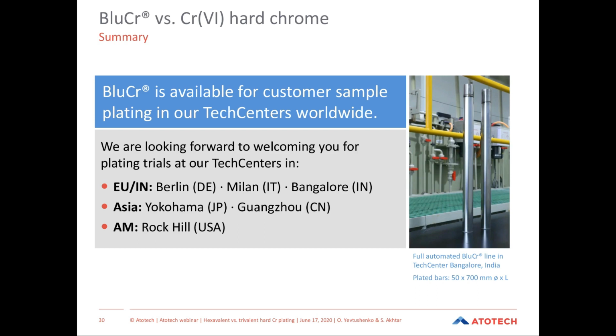Another question, does blue chrome also have uneven chrome layer thickness, especially on the ends? Maybe I can answer this question. In fact, I think the question is about the so-called dog bone effect. The performance of blue chromium is comparable to hexavalent chromium. So yes, if you have very long parts, then in areas of high current density, it might be necessary to apply some shieldings to achieve a homogeneous thickness distribution over the whole long part. But yes, this is definitely possible.